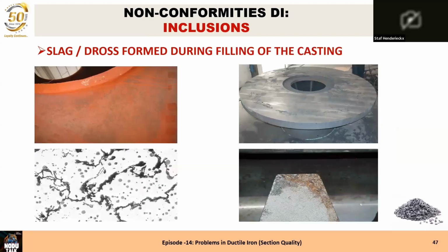So dross, we have discussed it already a few times. If you see a casting that had rusted a little bit, and you see these gray areas on the picture on the left top, that's due to the dross. Why? Dross does not rust, and the metal rusts. So if you see that, there is a lot of dross inside of that.